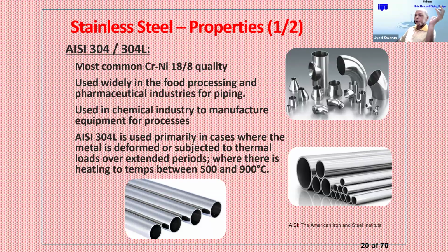Again coming back to what we said, engineering is optimization. We cannot select a material which is more expensive than required because a plant will become unviable. So it is always good to select the most optimum material, and we will select stainless steel only if it is really required, not just because I feel like selecting stainless steel or duplex stainless steel. The choice is always to go with the carbon steel welded pipe, number one. Second is carbon steel seamless pipe, number two. Then comes any other material like copper or brass or bronze, stainless steel or duplex stainless steel or nickel. But the cost keeps on increasing for these materials, and we should only select them if it is really required for the project.